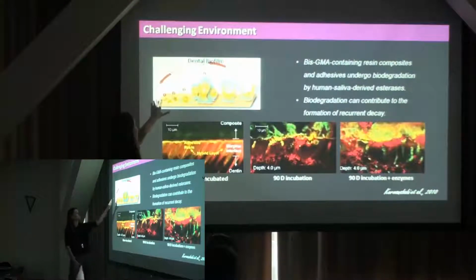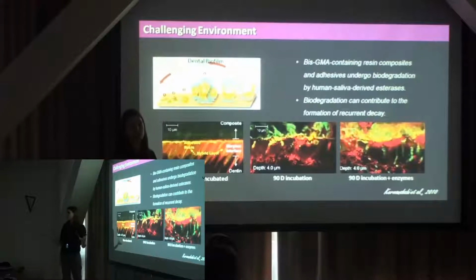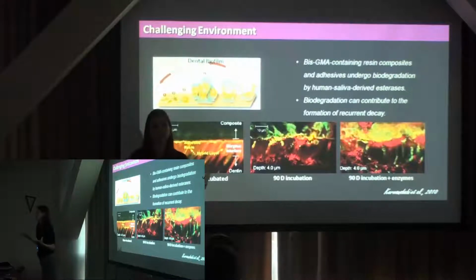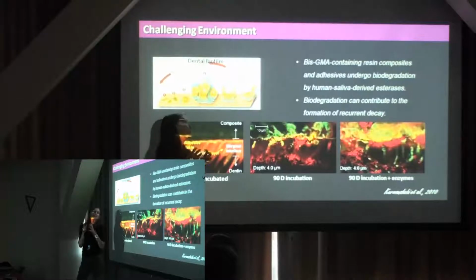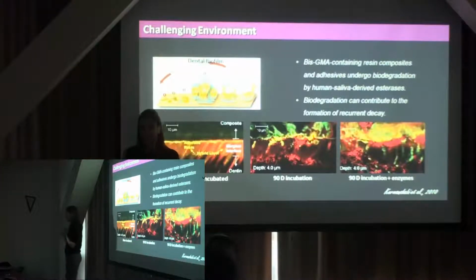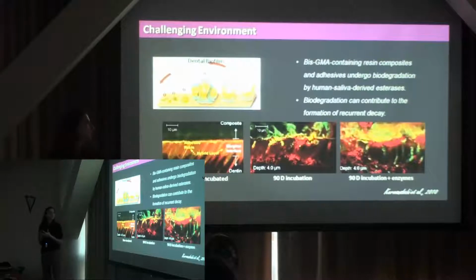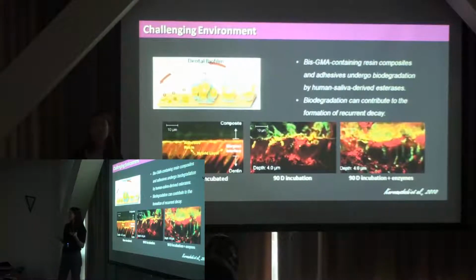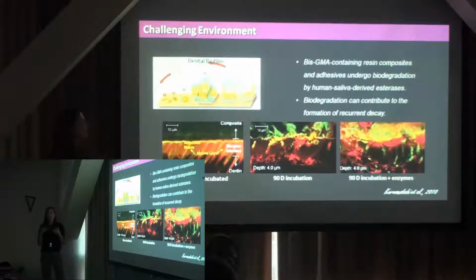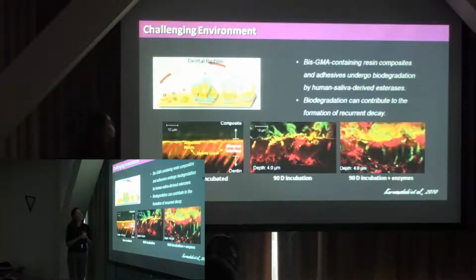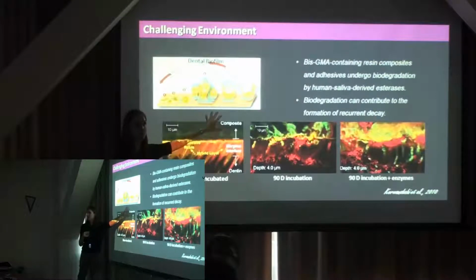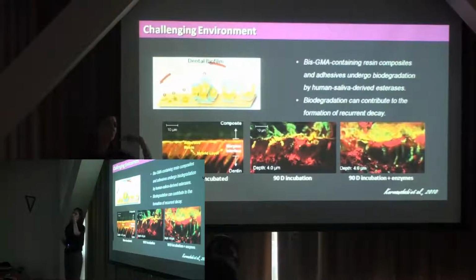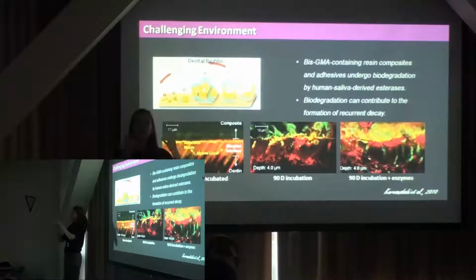Now, as I mentioned to you guys, the environment is very harsh. So you're biting over your teeth, you're biting over your fillings that you have right now. So this process of cyclic loading, chewing, is something that is very important. So some of these interfaces can fatigue by just continuous chewing over, and a lot of that we have tried to overcome. And one thing that we have an issue with in the mouth is the chemistry, and it's the bugs in there. So we have biofilm over the surfaces. So the biofilm will create over the surface of the tooth. It will create over the surface of the material. They can be slightly different.